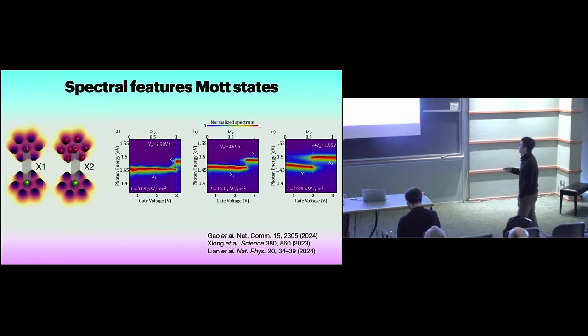If I increase the pumping power, I create more excitons that are occupying this lattice site. Then it would take fewer and fewer electrons to reach this single occupancy for the moiré lattice. So you see that the threshold for reaching this X2 transition becomes smaller and smaller, and also the gap size is different because eventually you will correspond to exciton-exciton correlation rather than electron-electron correlation as you pump very high. I didn't show it here, but even under zero doping, we can completely fill the system with excitons, so looking at pure exciton interaction. And from this X2 feature, we speculate that we form an exciton correlated state where the exciton transport is suppressed.